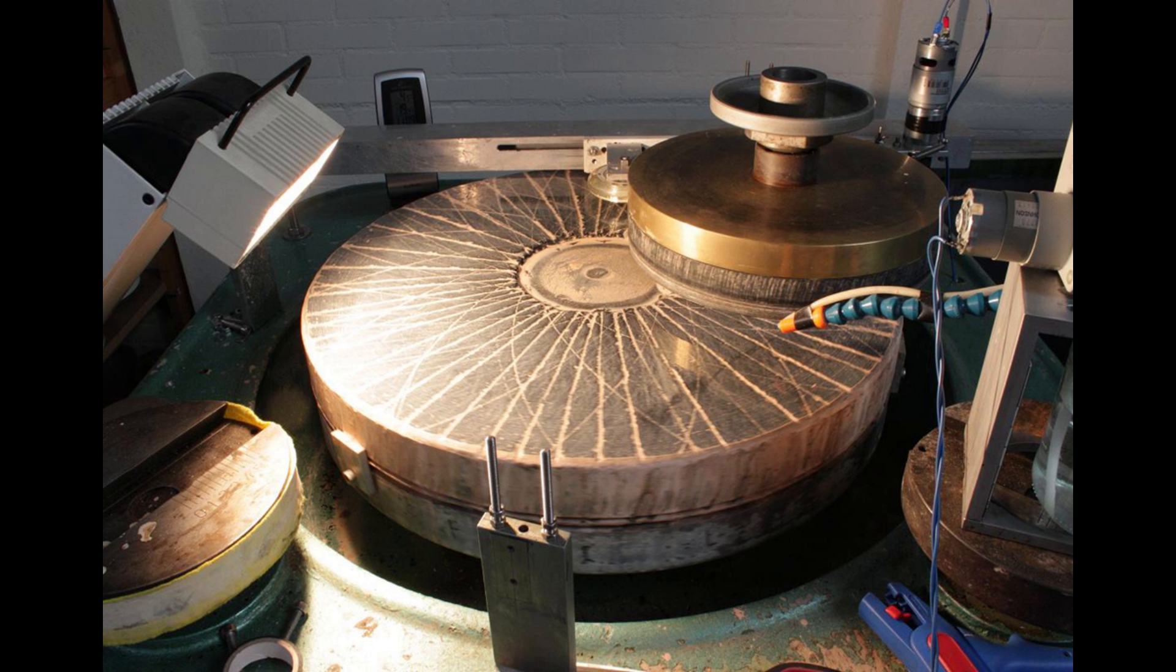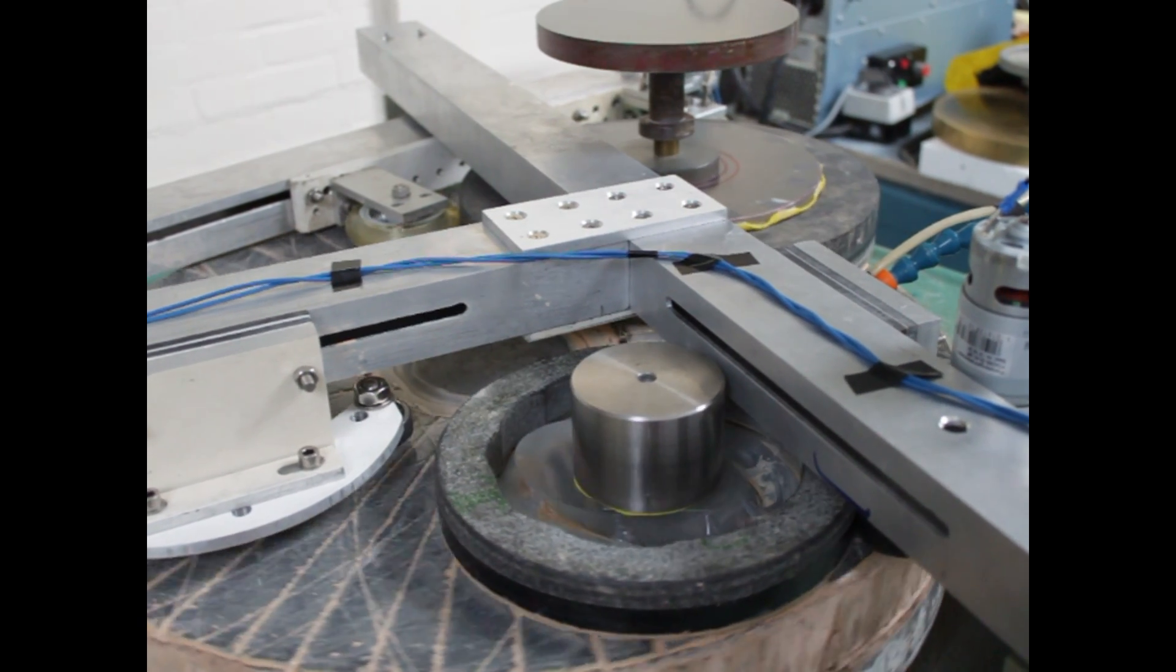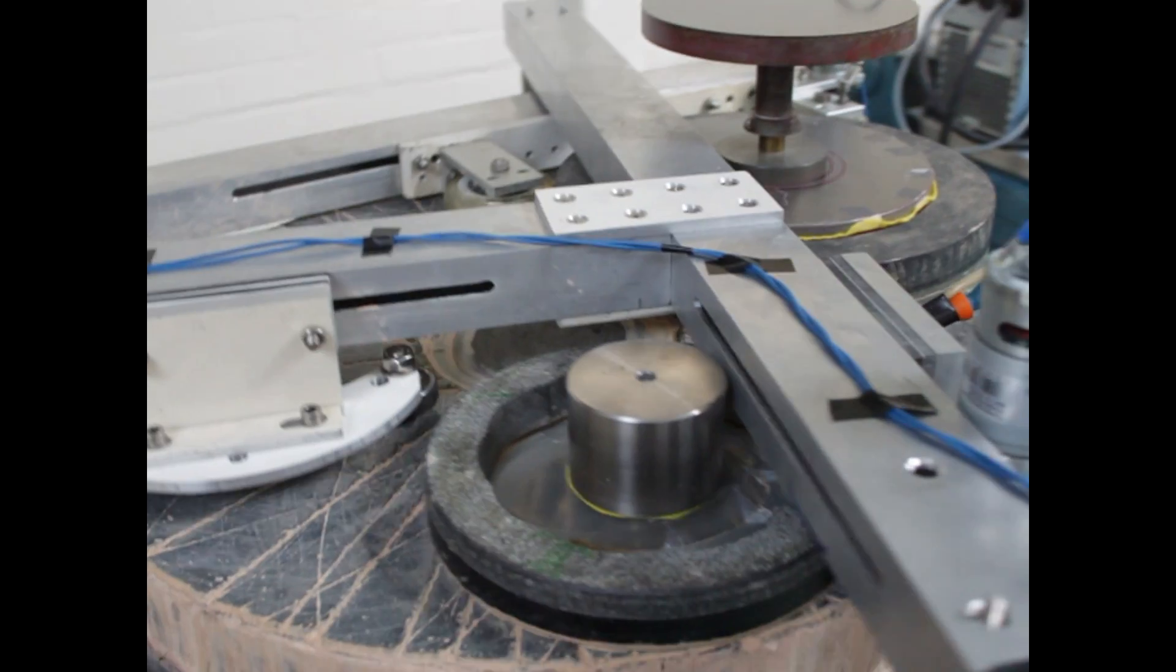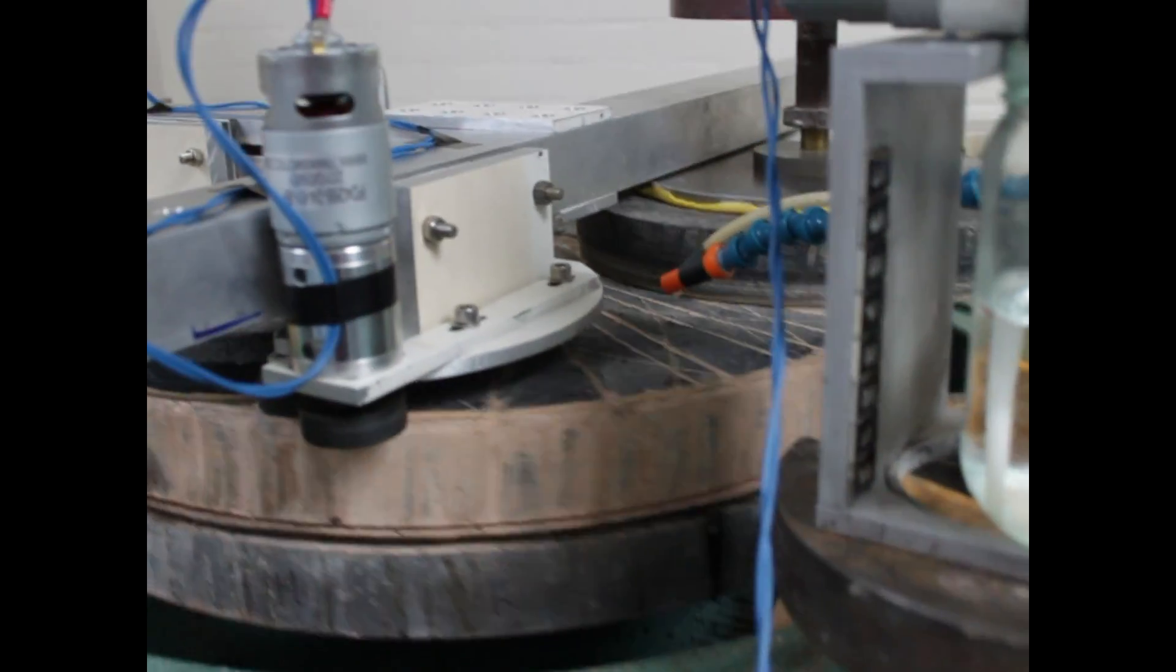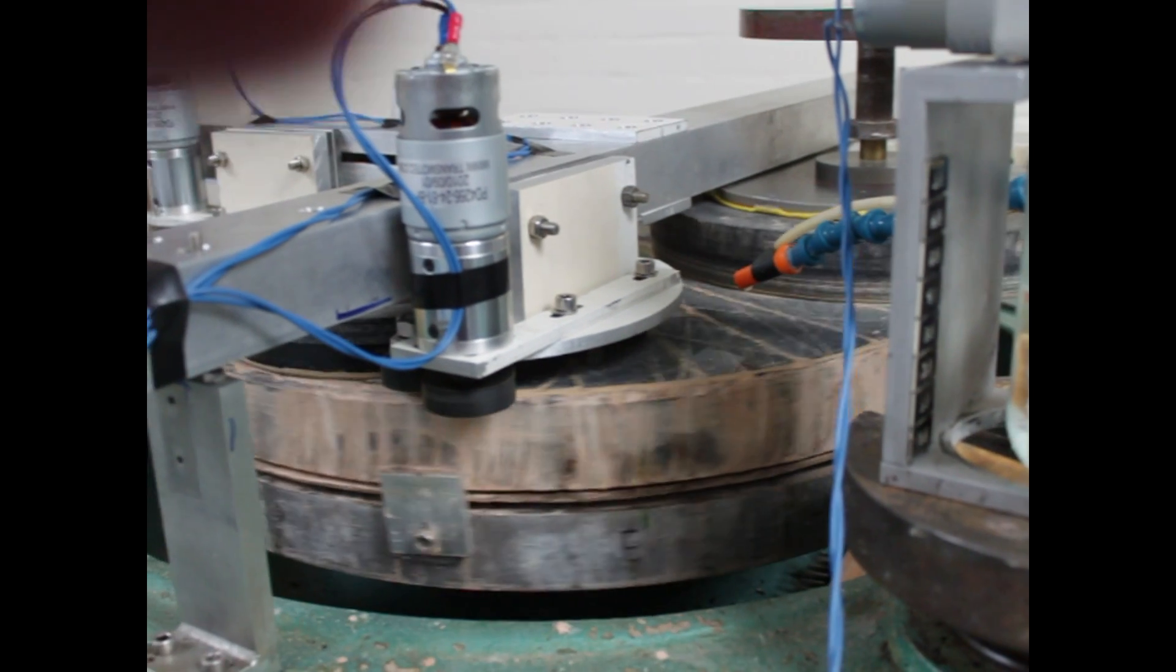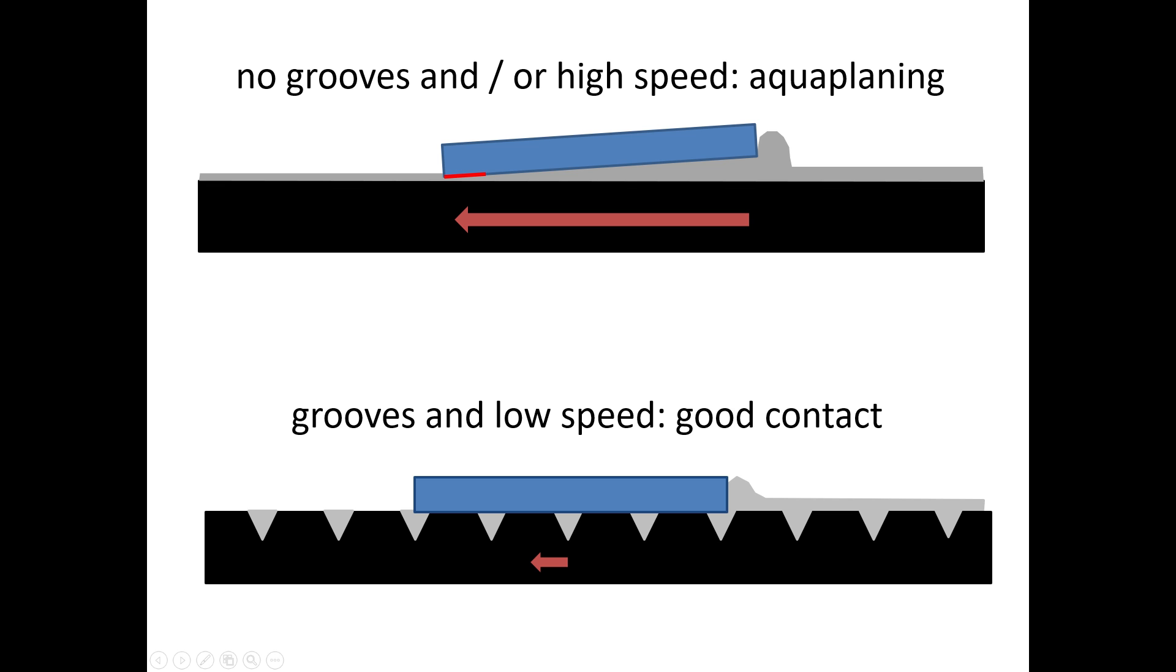There are a few things worth noticing, for example, the grooves in the pitch surface. These grooves actually serve a similar purpose as the grooves you find on a car tire. They allow for good contact between the pitch and the optical surface. As I mentioned earlier, the abrasive used is an aqueous suspension with micron sized particles. In order to make physical contact between glass and pitch under continuous movement, the water in the suspension has to be able to quickly flow away from the contact area.